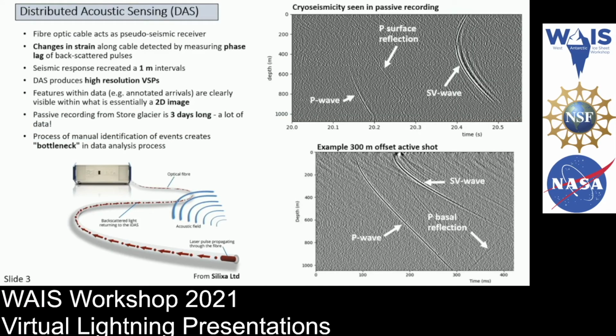So, just in case anyone is unfamiliar with distributed acoustic sensing, or DAS, it is a relatively new technology that uses a fiber optic cable itself as a pseudo-seismic receiver. What this means is that changes in strain in the optical fiber caused by an acoustic field, in this case a passing seismic wave, create a phase lag in the backscattered pulses of light as they travel through the cable, and this phase lag is used by what's called an interrogator unit to then recreate the seismic signal. This effectively turns the cable into a very densely sampled string of geophones.